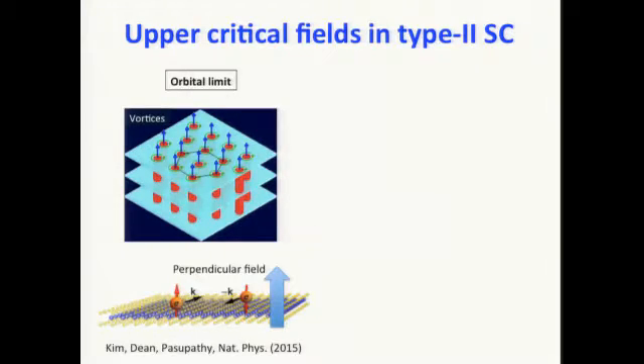So what limits the upper critical field of a type 2 superconductor? There are two mechanisms. One is called the orbital limit. What it means is that if you apply an external magnetic field to a bulk superconductor, vortices are formed. Inside the core of each vortex, this red cylinder here, the material is normal, surrounded by some circulating supercurrent. And when the magnetic field keeps increasing, these normal cores start touching each other, then it turns into a normal metal. And this corresponds to the case of a perpendicular magnetic field applied to a single layer of niobium selenide.